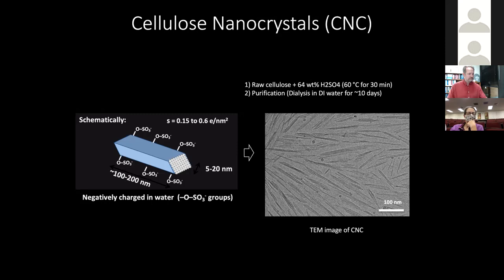By themselves, no, because at a certain point there would be a problem that we saw at the beginning, which is funny: our films were becoming moldy because we weren't treating them. Bacteria start to act, and since they are in suspension, they became moldy because the bacteria were growing inside. Then we learned to put one drop of chloroform for 2 liters of CNC, and then they were fine. But at the beginning, we got them moldy. So it tells you that microorganisms digest them.